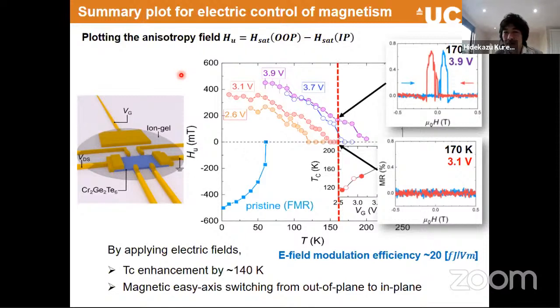But even just magnetic anisotropy in the bulk, or sorry, the undoped insulating regime, is not described by a single ion anisotropy. Looking at the literature, it's definitely exchange anisotropy, that's for sure. Yes, anisotropic exchange interaction because of this 2D nature. So when we dope and see in-plane anisotropy, it becomes bigger, and I have no idea why this value is even bigger than the one that we have in the undoped case. I actually don't know how to look into it. If you have any suggestion or any way to look into it, I'm very much looking forward to hearing it, because you're one of the experts.